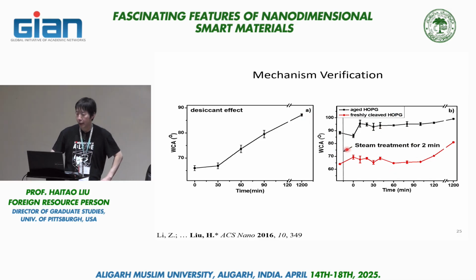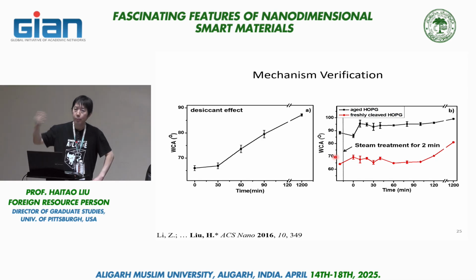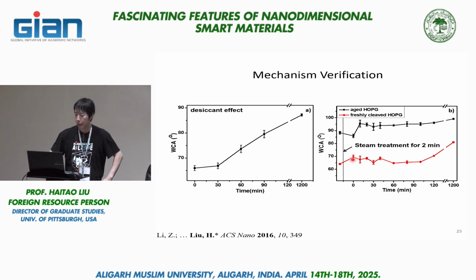And also another control where we're not going to do the low temperature experiment, but instead we simply expose the graphite to high humidity. And this high humidity can be created by exposing it to steam, so 100% humidity. And in this case, you find that the high humidity environment also protects the surface of graphite: within 120 minutes, there's no increase of contact angle to 90 degrees. And in the control experiment, we expose the steam to air-aged graphite. We find the surface remains hydrophobic. And this indicates that steam doesn't damage the surface. It's not a chemical damage that makes the surface hydrophilic, but rather something intrinsic about the relative humidity of the environment that keeps the surface in a relatively pristine state.